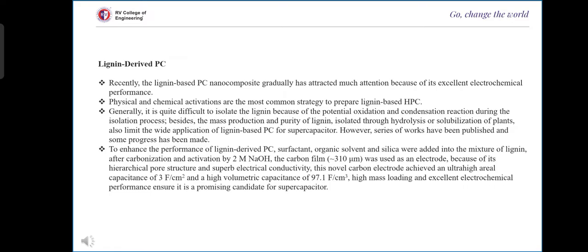However, a series of works have been published and some progress has been made to enhance the performance of lignin-derived porous carbon. Surfactant, organic solvents, and silica were added into the mixture of lignin, followed by carbonization and activation by 2 molar NaOH. The carbon film, which is approximately 310 micrometers thick, was used as an electrode. Because of this hierarchical porous structure and superb electric conductivity, this novel carbon electrode achieved an ultra-high areal capacitance of 3 F per centimeter squared and a high volumetric capacitance of 97.1 F per centimeter cubed. High mass loading and excellent electrochemical performance make it a promising candidate for a supercapacitor.